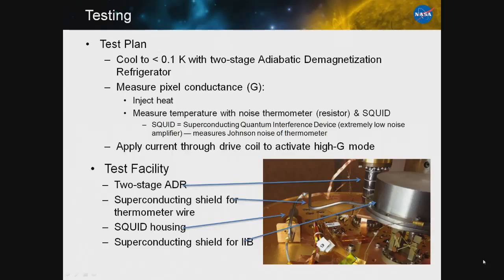So the plan is to test our device. We'll cool it to below 100 millikelvin with a 2-stage adiabatic demagnetization refrigerator. We will just do a simple conductance measurement, inject heat through one of the resistors, and as I said, use the noise in the other resistor with a SQUID, which we have right here, to read out the Johnson noise and measure the temperature of the test chip, which is inside this shielded box here that's driven down by the ADR. And of course, we can apply current to the drive coil and switch the switch to the closed state and measure the conductance in both states.